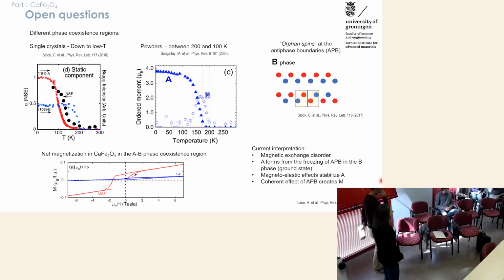I have a couple of questions which I'm not sure are related or not. The first one is regarding the growth. I think you have identified the presence of a strong calcium ferrite phase that is quite thick. Your layer is a few nanometers, maybe 20 or 30 nanometers, or 10 nanometers. So that means that during the growth, you should have an excess of iron.